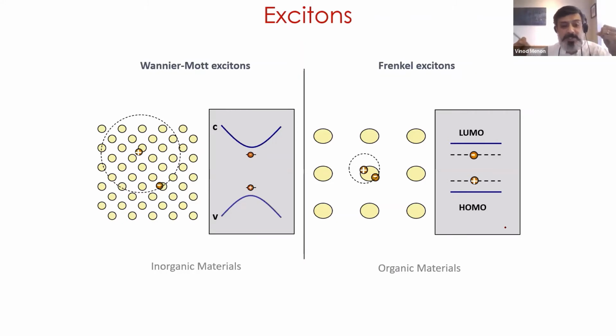Typically, the hole is heavier than the electron, so the electron is usually going around. In this case, the Coulomb energy essentially creates a quasi-particle whose energy is less than the actual band gap. So the band gap is here, the exciton energy is lower. And this lowering is the result of the Coulomb attraction. You reduce the overall energy of the system by this Coulomb energy that holds them together.